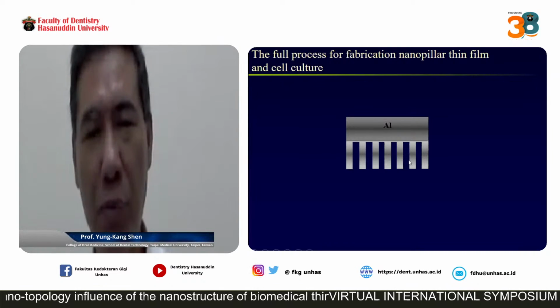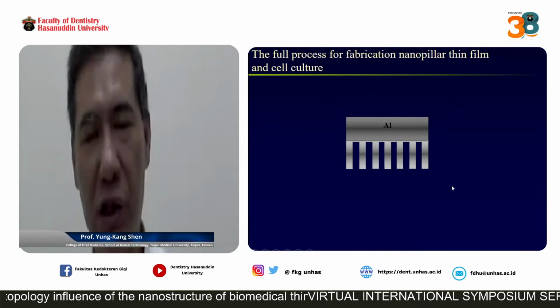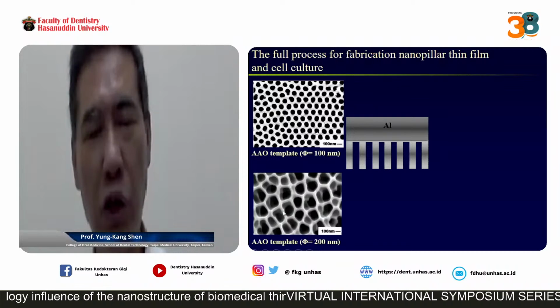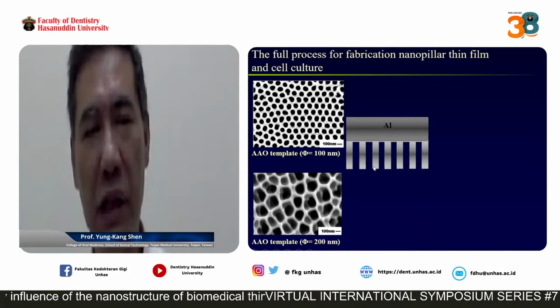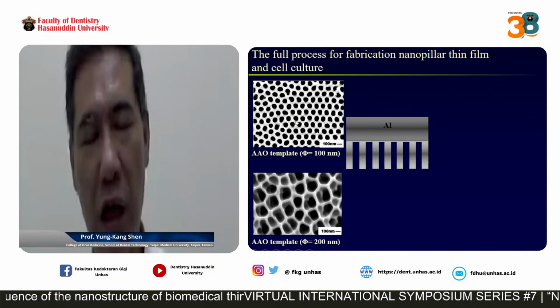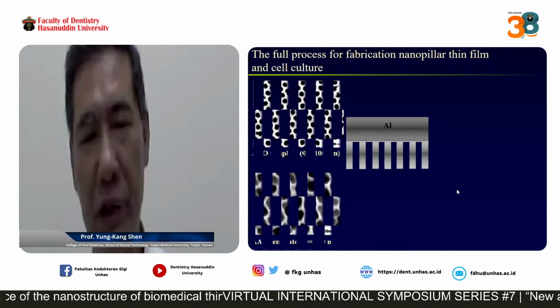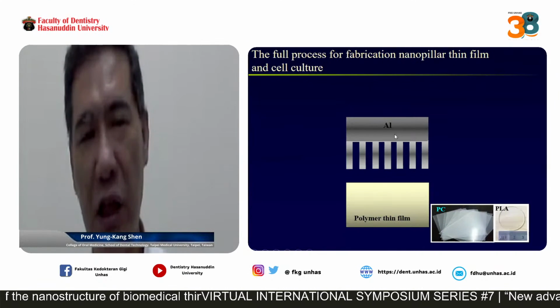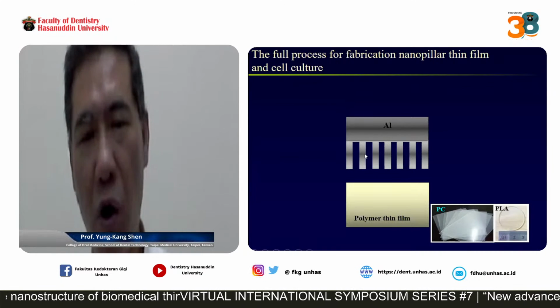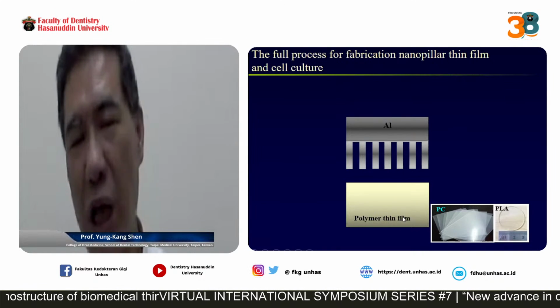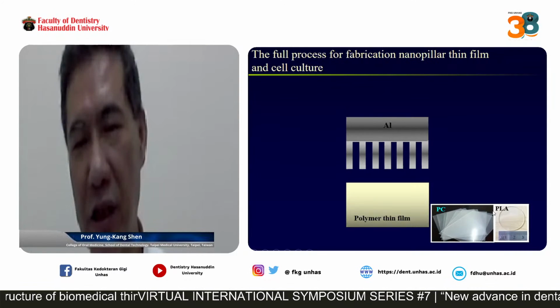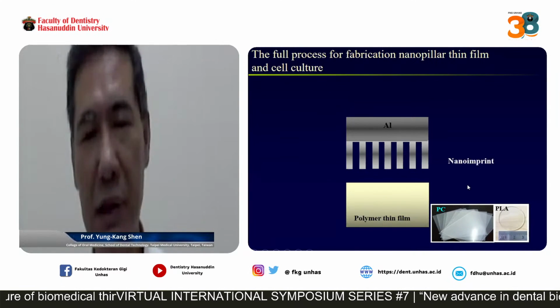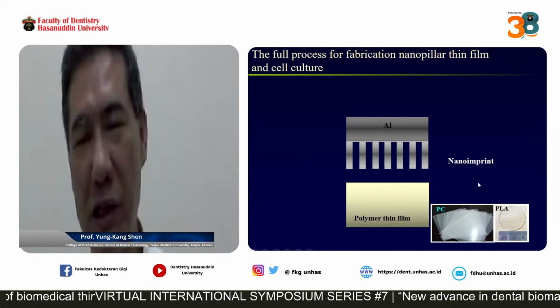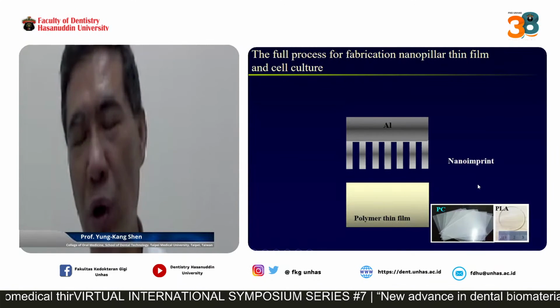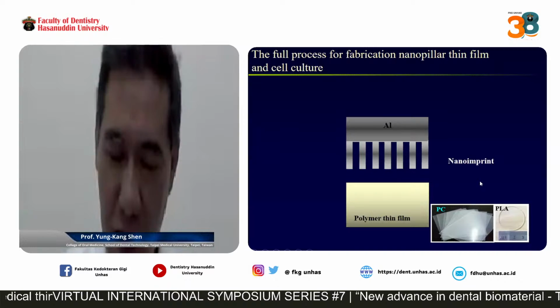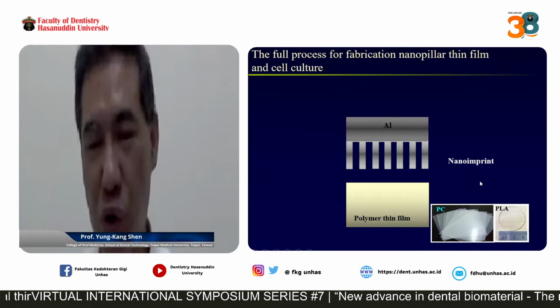Now we use this template as the imprint master. You see, we can use the SEM to see the nano holes on its surface. This is 100 nanometer. This is 200 nanometer. And we use this as the imprint to imprint the nano holes on the polymer thin film. There are two types of polymer thin film used here, PC and PLA, which are biopolymers. So you can see we do the nano imprinting method, like the traditional Chinese use of a stamp adhesion on the paper to show the name.